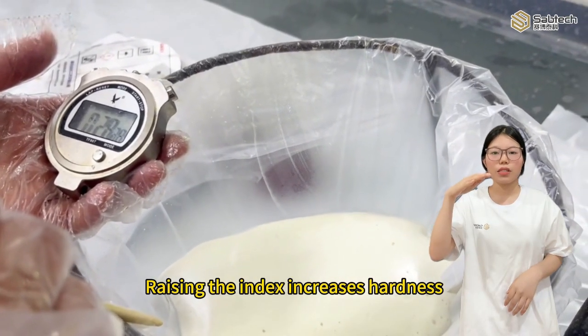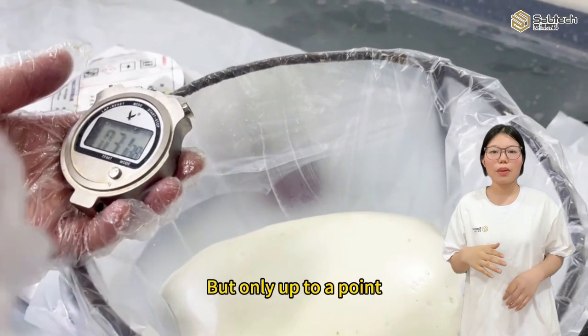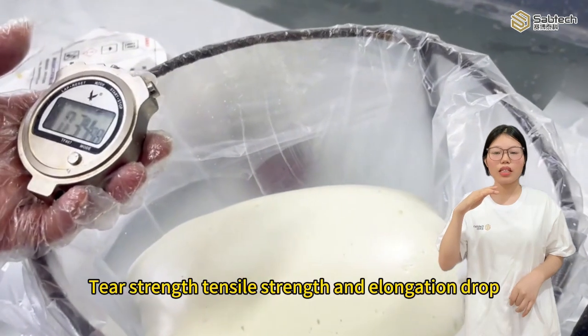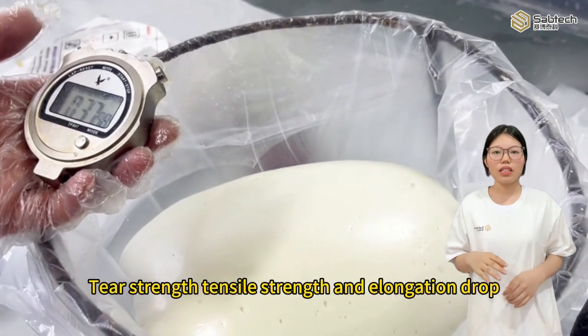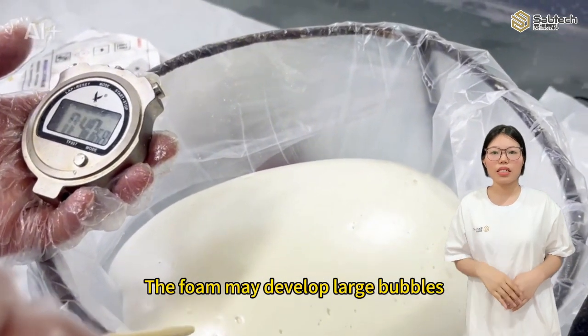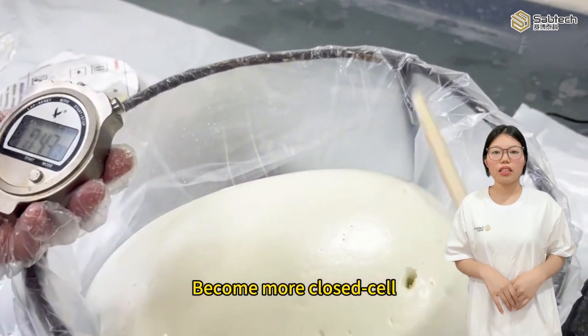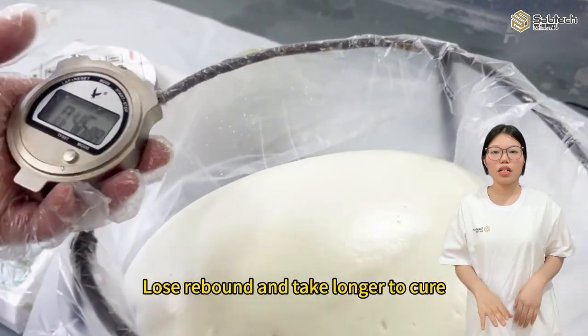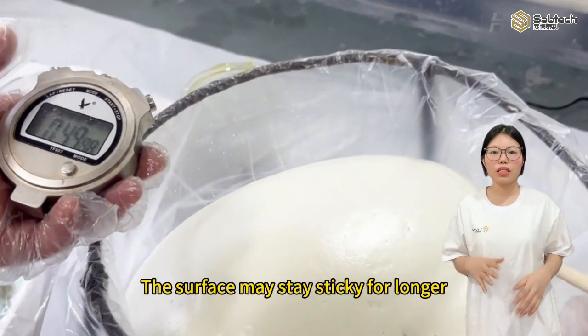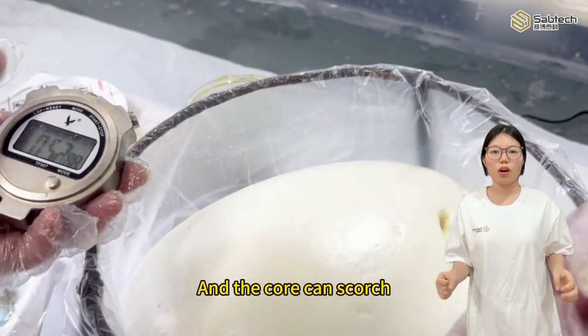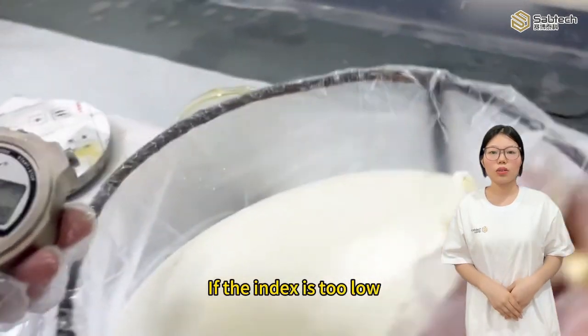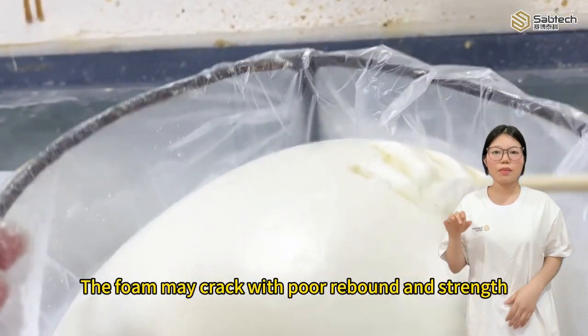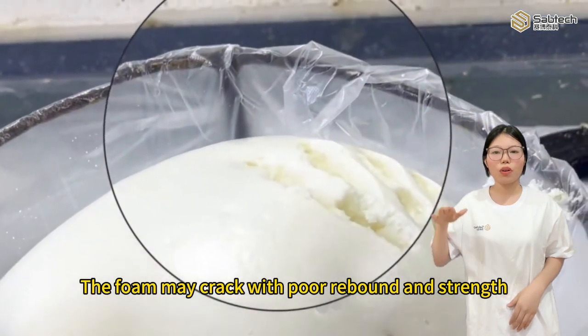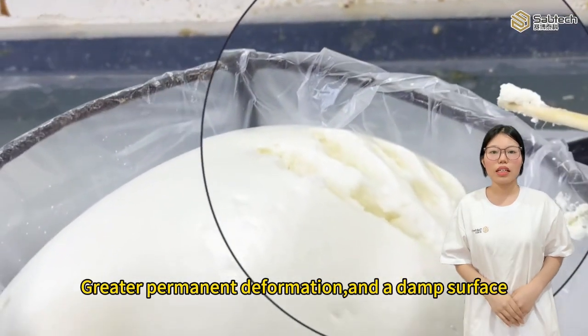Raising the index increases hardness, but only up to a point. Beyond that, tear strength, tensile strength, and elongation drop. The foam may develop large bubbles, become more closed cell, lose rebound, and take longer to cure. The surface may stay sticky for longer, and the core can scorch. If the index is too low, the foam may crack, with poor rebound and strength, greater permanent deformation, and a damp surface.